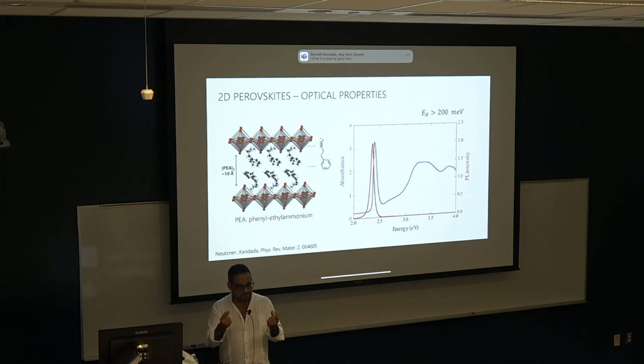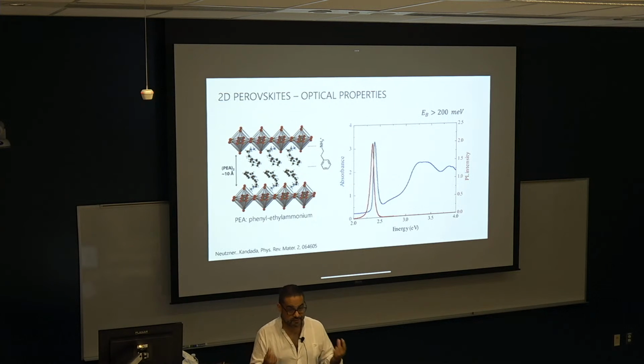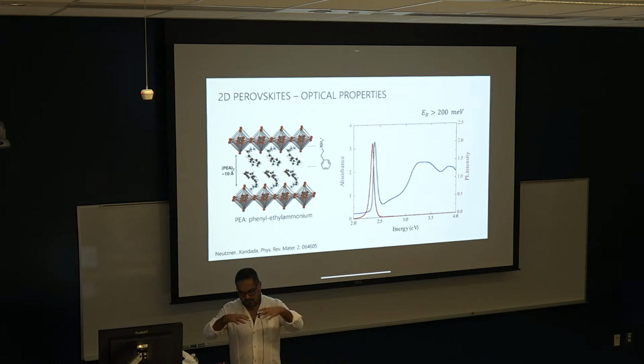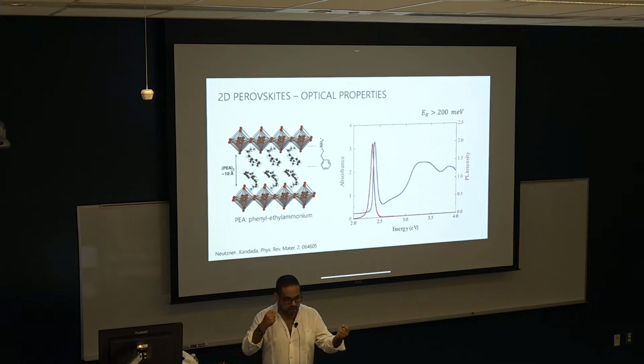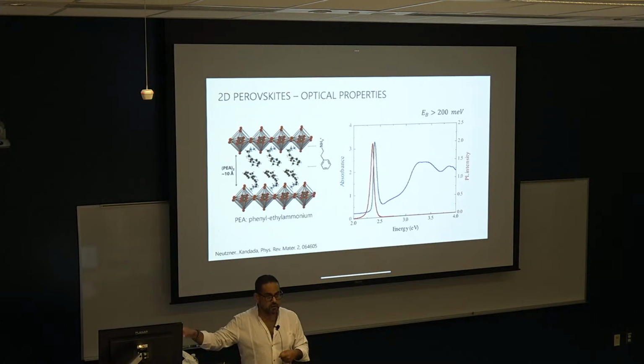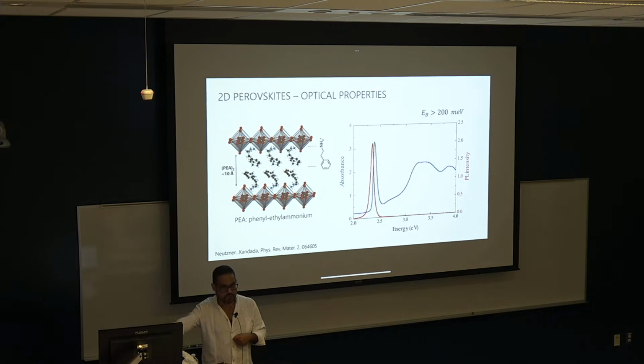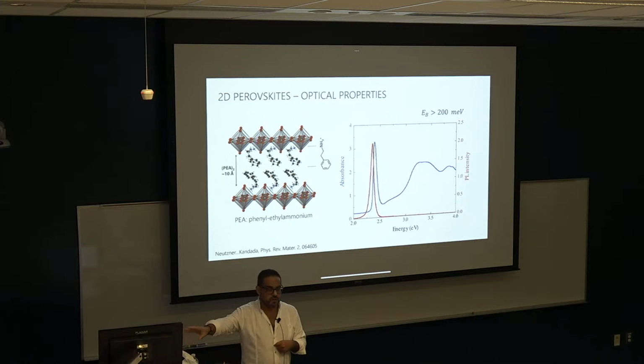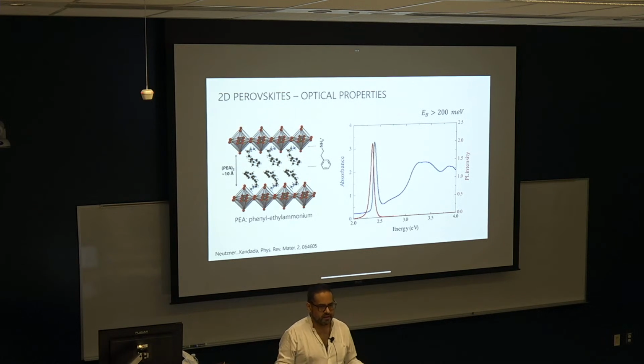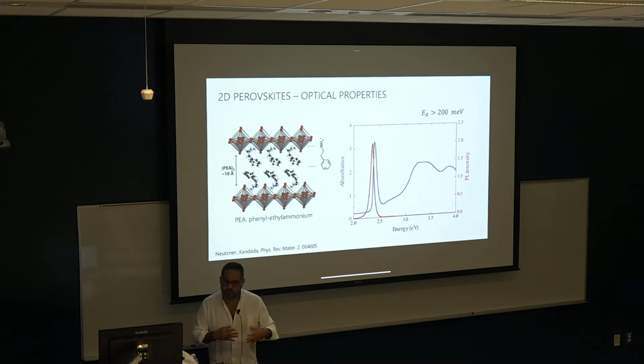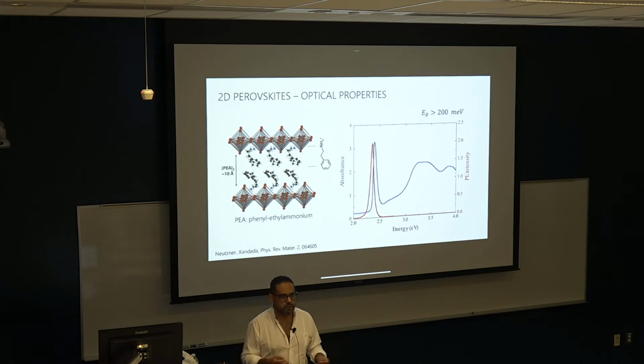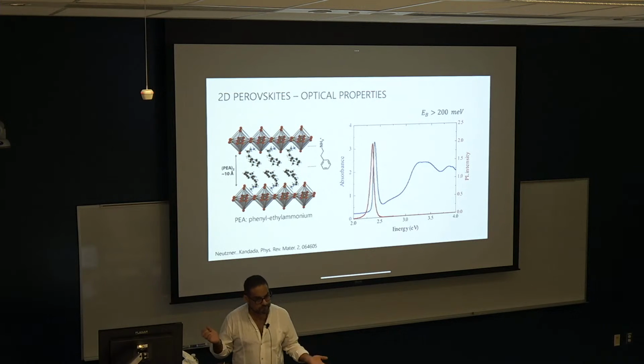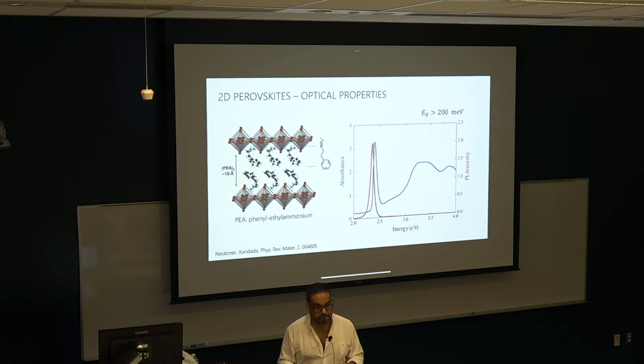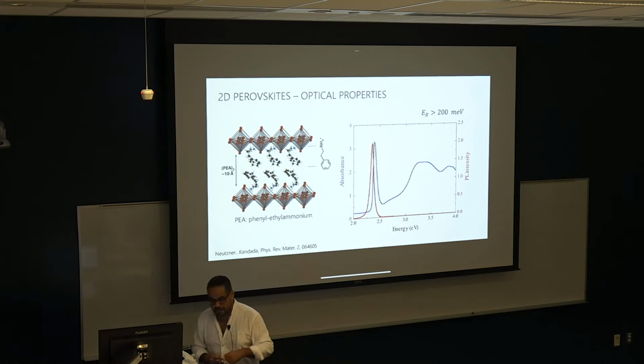Whereas in these materials, you have very strong quantum confinement effect, the 2-dimensional density of states, but you also have very strong dielectric confinement. The electron and the hole, because of vacuum around the single layer, have very, very strong Coulomb interactions. So in bulk lead iodide perovskite, hybrid perovskite derivatives, you have exciton binding energies of the order of kT at room temperature, somewhere between 20 to 40 milli-electron volts, around there. Whereas in these 2-dimensional materials, exciton binding energies go to 250 milli-electron volts, very strong effects. So you have very strongly bound excitons that are manifested in the optical properties.